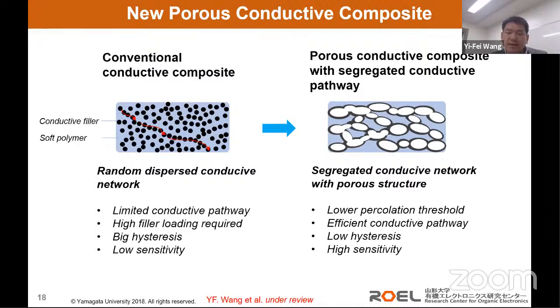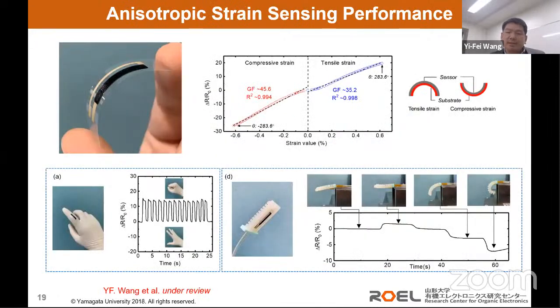So here I do not put so many details, but we can also see some devices fabricated based on this composite. The first one shows very good anisotropic bending sensing performance. When the sensor bends outward, there is a tensile strain applied on the sensor, and we can see an increase of the resistance.